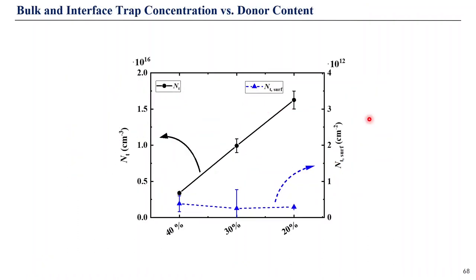That's why we analyze here only the dominant contribution from bulk and surface trap-assisted recombination and see how dilution of the donor concentration content affects them. So we see that pretty much nothing happens with the concentration of surface traps. However, the bulk traps steadily increase as we dilute donor. And keep in mind that we use the same materials here for all devices. The only difference is a lower donor concentration.